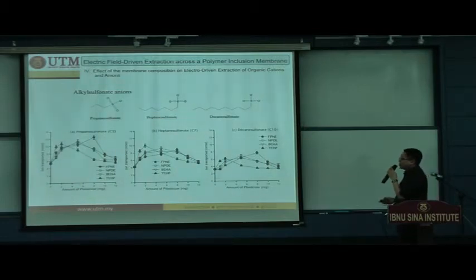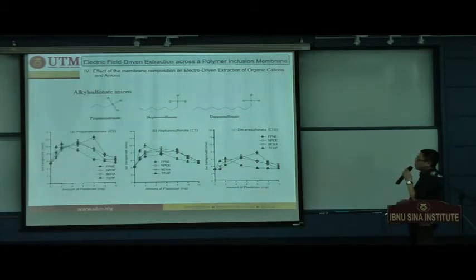For example, for the less hydrophobic MPNE with a log P value of 2.7, they only perform the best when you use 8 milligrams of plasticizer in the membrane. But on the other hand, the most hydrophobic THP only requires a very tiny amount of 2 milligrams to be present in the membranes.